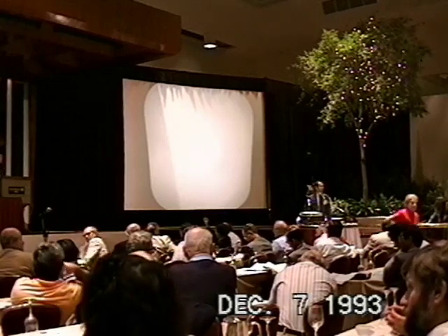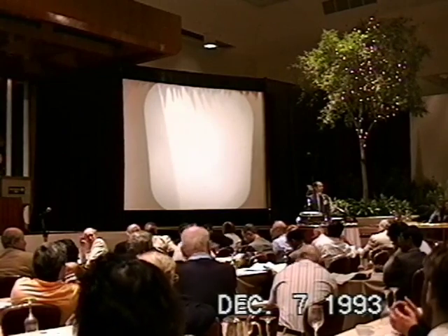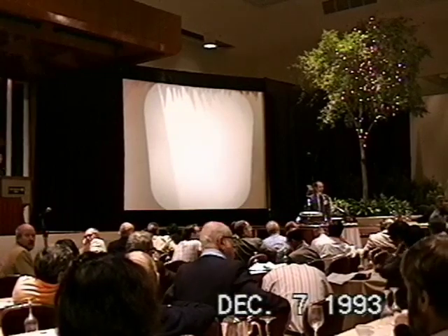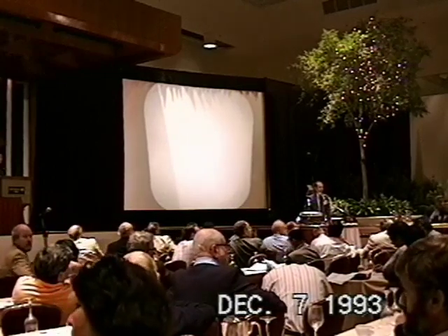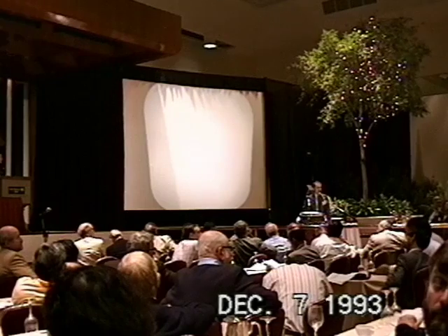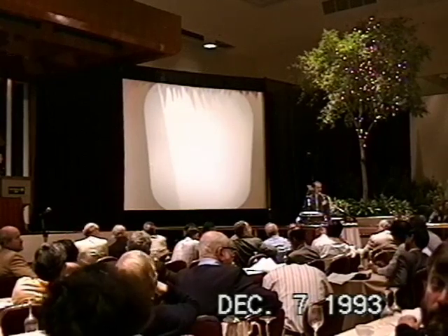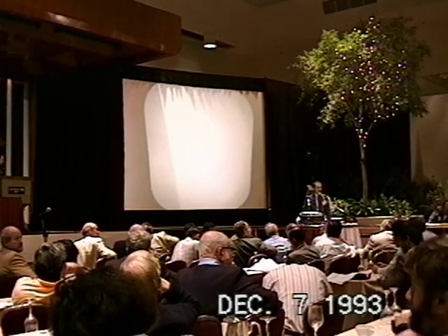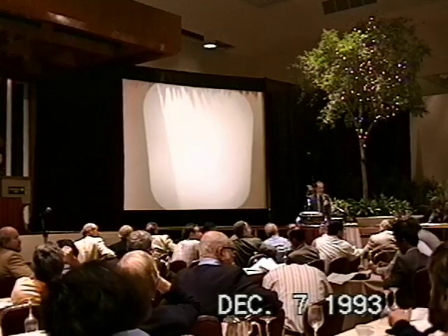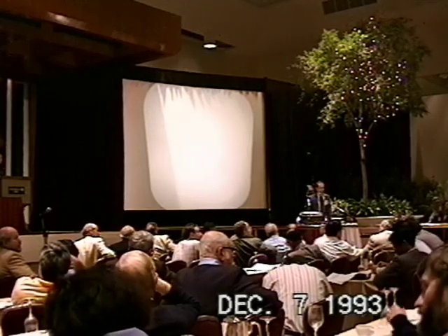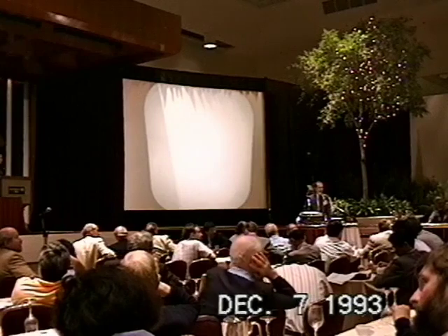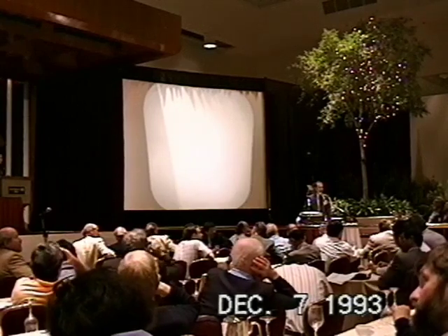I have a question. In the experiment where you're using the Johnson-Matthey wire, where the wire recrystallized, what range of temperatures was experienced by that wire? Do you know? The reason I ask is that in some of the very early palladium that was returned to Johnson-Matthey by Fleischmann and Pons, we observed recrystallization characteristic of temperatures having been generated in the electrode of between 200 and 300 degrees centigrade.